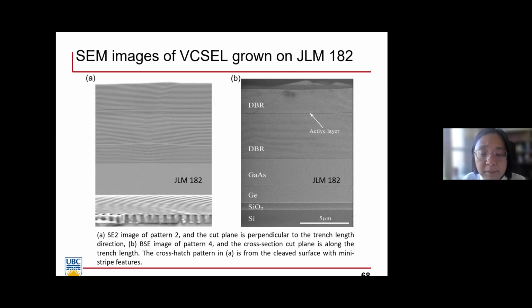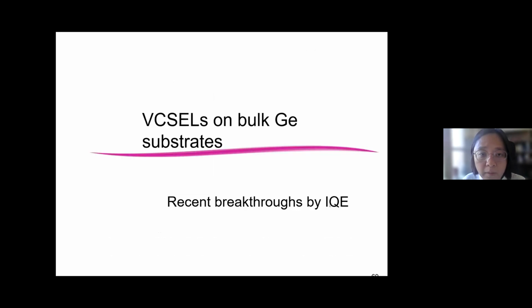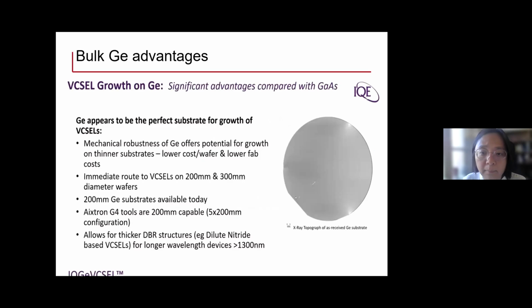And besides this, with germanium as an intermediate or transition layer, we have a recent breakthrough by IQE, a UK company, where they just use the bulk germanium, because silicon adds another layer of difficulty. Silicon substrate has a different thermal expansion coefficient, whereas germanium and gallium arsenide match very well. So they use germanium, and you can do 8-inch and even 12-inch germanium wafers.